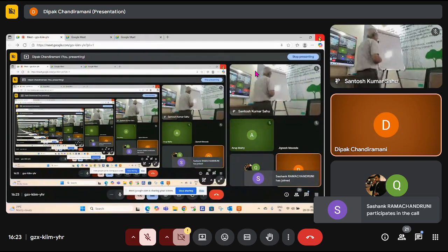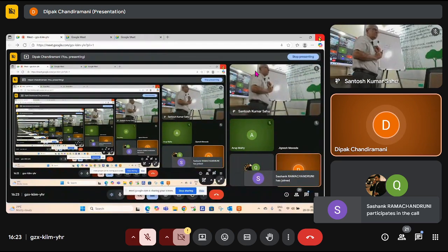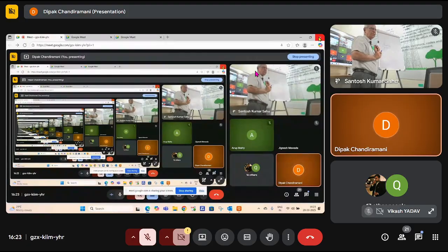Okay. Firstly, there's a clearance between tube and tube hole, which I know more or less. So I do what I call a light expansion, and I make this touch. After that comes the next stage where I do more expansion, and then the thinning of the tube starts. That thinning percent is what we are talking about as expansion. So 2-3% makes it a light expansion to touch. When you go to 6-8-10%, then it has thinned the tube.